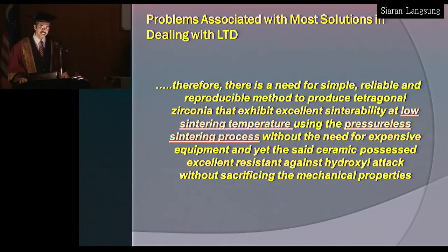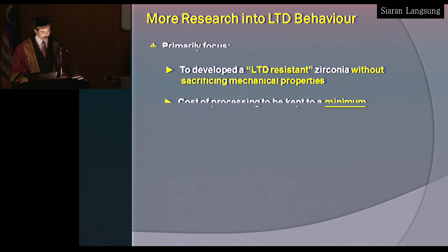So therefore, there is a need for a simple, reliable, reproducible method to produce tetragonal zirconia that exhibits excellent sinterability at low sintering temperature using pressureless sintering process. All right, so we don't want to use expensive equipment. We want to keep the temperature low, and we don't want to use expensive chemicals. And so we go back to the drawing board.